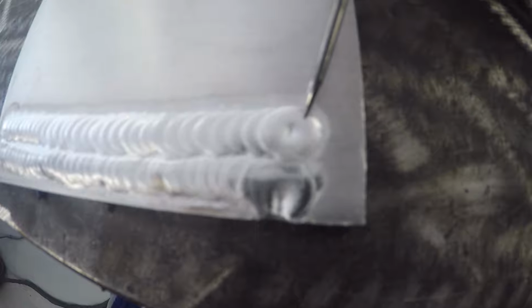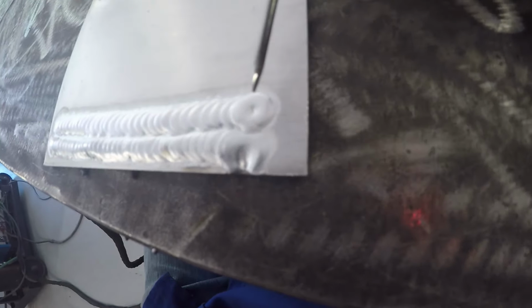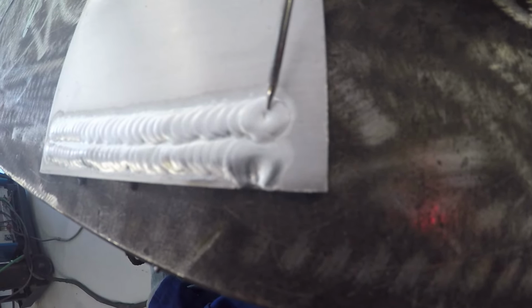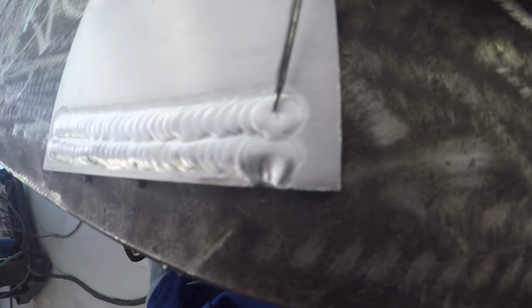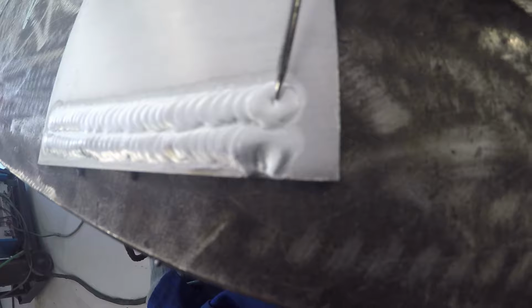And then towards the end of the weld here, we have our crater. Because of that real heavy shrinkage that we get on aluminum, we need to be careful of developing a crater. So at the end here, we want to add a little bit more filler, which I actually have a pretty good dimple here. I'll try to do a little bit better job next time. But basically, we want to try to eliminate this as much as possible, because this is where a lot of the cracking that develops in aluminum will start, in this crater.